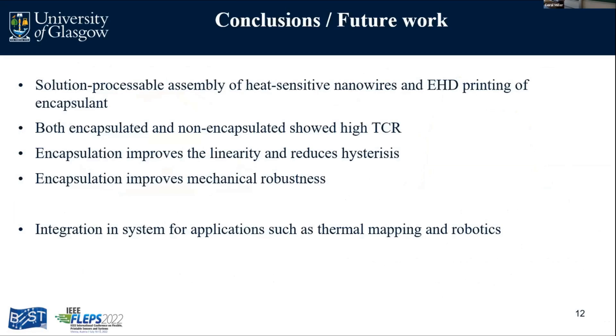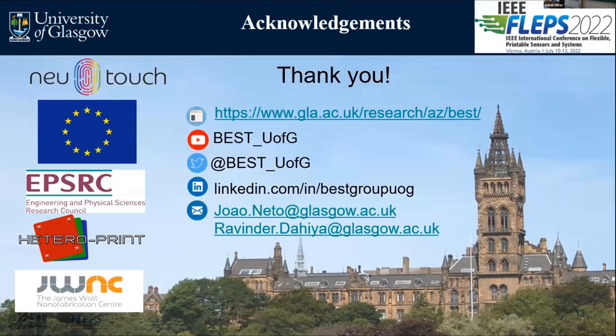The printed encapsulation layer thickness is around 2 microns. In summary, I have shown you the solution-process assembly of heat-sensitive nanowires and the electrohydrodynamic printing of the encapsulant. We saw that both encapsulated and non-encapsulated devices showed good sensitivity, and that encapsulation really improves linearity, reduces hysteresis, and improves the mechanical robustness of the device. In the future, we are planning to integrate these devices for applications such as temperature mapping around robots. I'd like to acknowledge all the funding that made this work possible and thank my group for all their help.